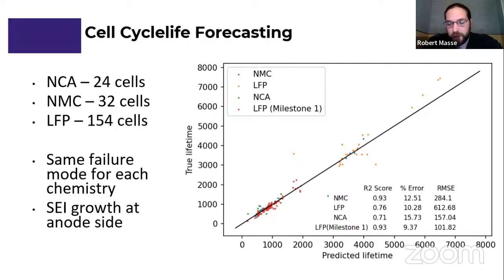And what we were able to do is get some additional data from Sandia National Lab and a couple other sources and look at different chemistries and different load profiles. So we're basically able to expand that result to additional chemistries and temperatures and operating conditions. Basically, what we found is that the same model, the weights might be different, but the model more or less stays the same. And we believe the reason for this is that it's got the same failure mode for each of these